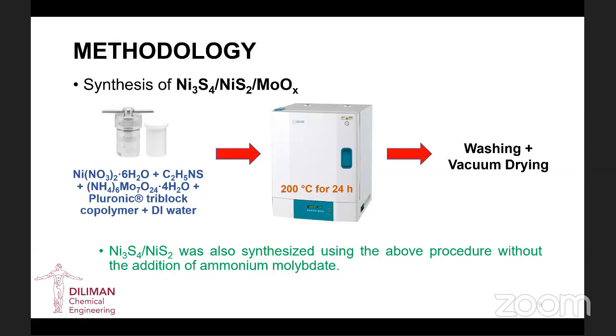After which the mixture was placed inside a furnace or oven at 200 degrees Celsius for 24 hours. And then the resulting black precipitate was washed with DI water and ethanol and dried in a vacuum oven for 12 hours. So the obtained final product is the polydymite nickel disulfide molybdenum oxide composite.